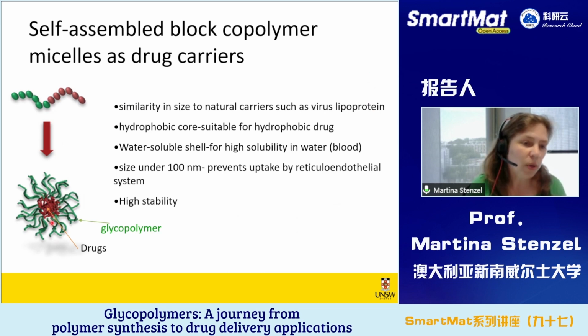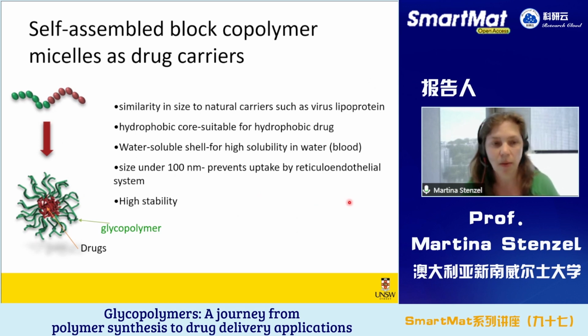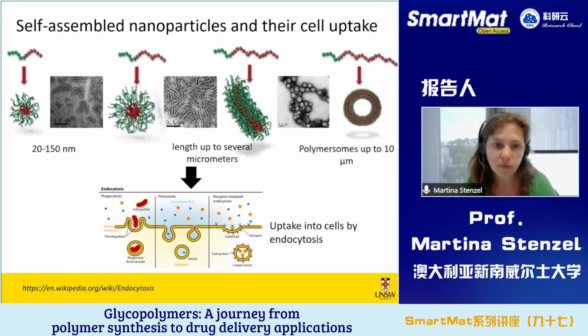We have a hydrophobic core, and that hydrophobic core allows us to contain hydrophobic drugs. At the same time, we have a water-soluble shell, and this water-soluble shell ensures high water solubility. We also have a size below 100 nanometers, which makes sure that these nanoparticles can circulate in the bloodstream for a very, very long time and are not really detected by the immune system. Moreover, we have very high stability.